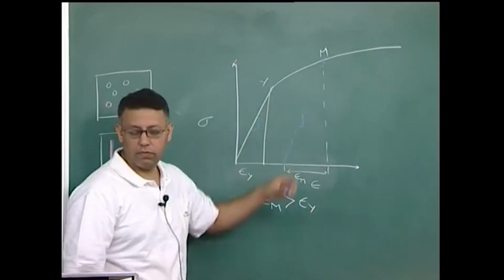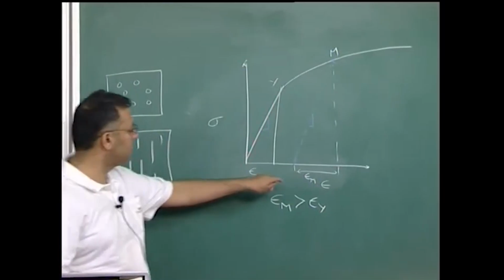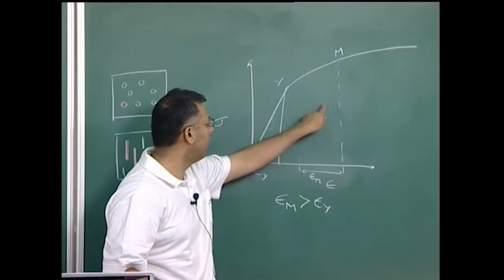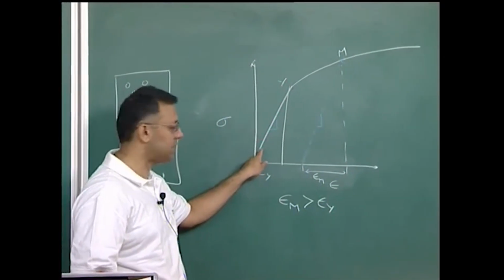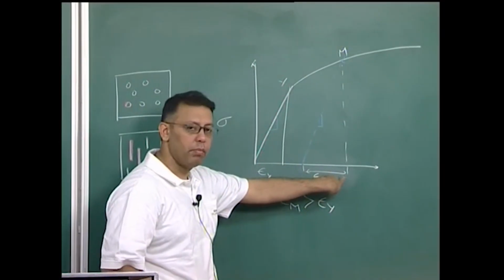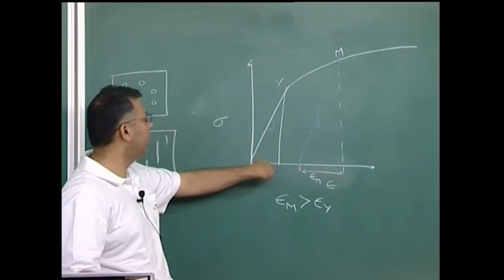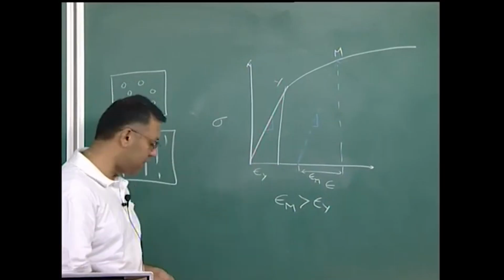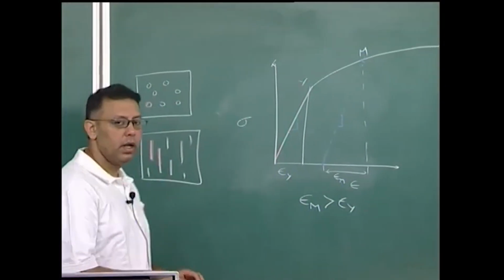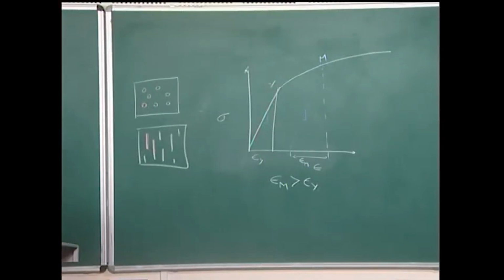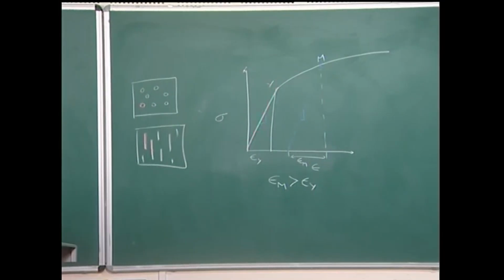actually this region, which is the blue region, that means by drawing similar triangles and unloading, with the unloading curve being parallel to this original elastic line, I observe that actually I recover more strain here as compared to if I unload from point y. So, in some sense, in the sense of the strain obtained, the so called plastic region is more elastic than even the elastic region, and therefore, I need to call this so called plastic blue part of the curve as actually elastic plus plastic and not merely plastic.